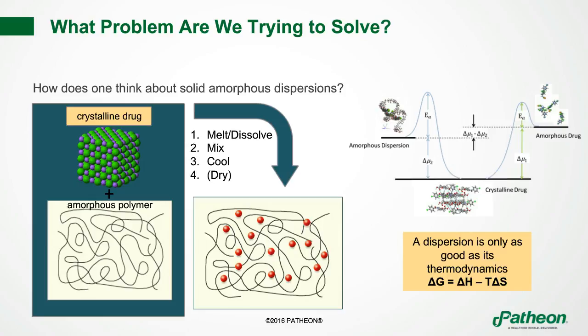As I can see on the right-hand side of the screen, I have an amorphous dispersion. Its energy is somewhat higher than the crystalline drug, and somewhere in between the crystalline drug and the amorphous drug energy. So the stability of this amorphous dispersion is only as good as the thermodynamics. If we have a stable amorphous dispersion, we expect good stability and perhaps good dissolution behavior.